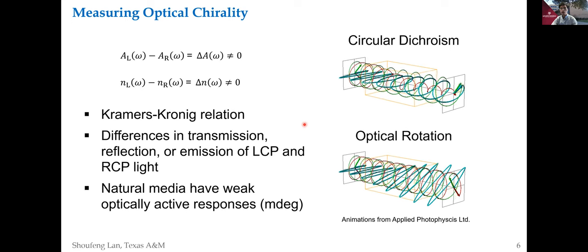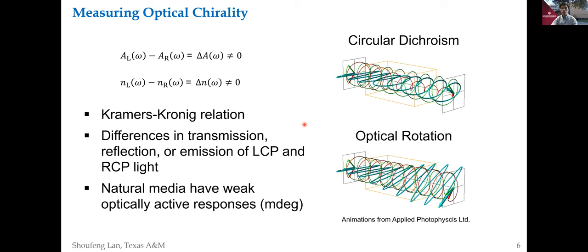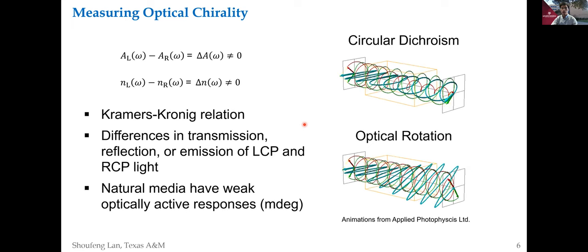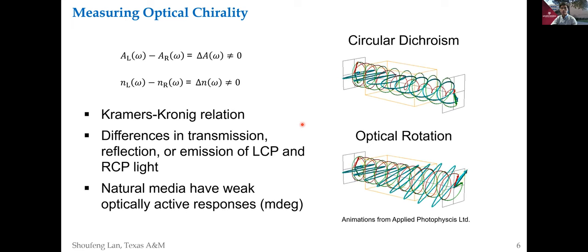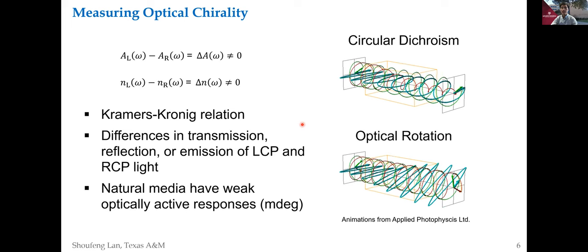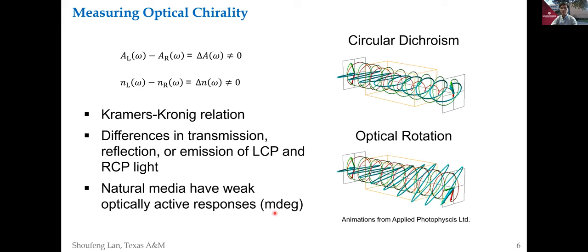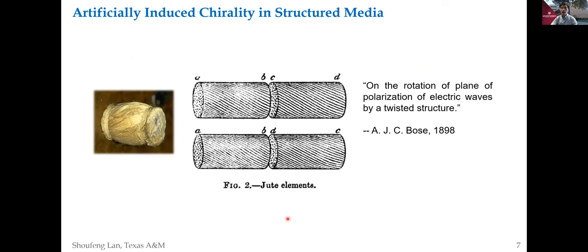And the best practice for optical chirality is to measure the difference of the LCP and RCP light in terms of transmission, reflection, or emission. And the optical activity for natural chiral materials is around 1 millidegree. For stronger chirality, one can artificially induce the chirality by structuring the optical medium. For example, in 1898, Bose discovered that the polarization of millimeter waves will rotate by an angle when passing through twisted jute elements. The jute is just a fiber from plants.